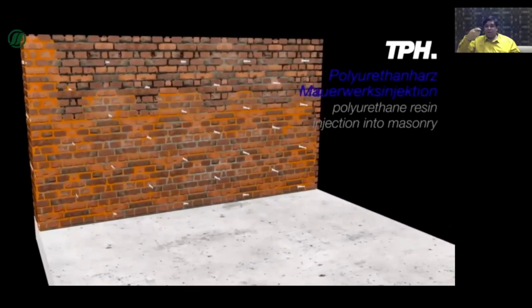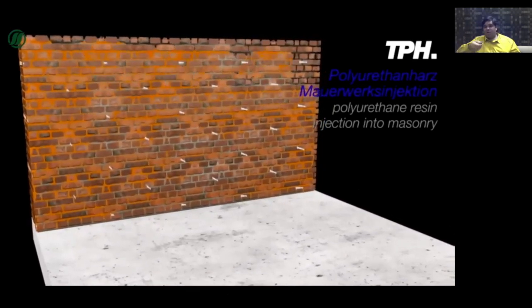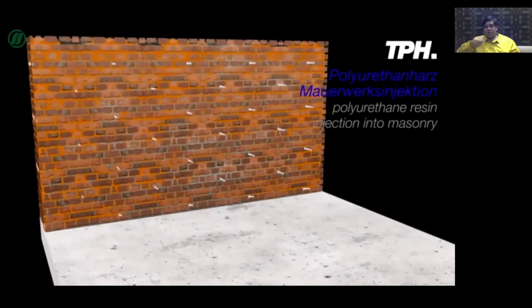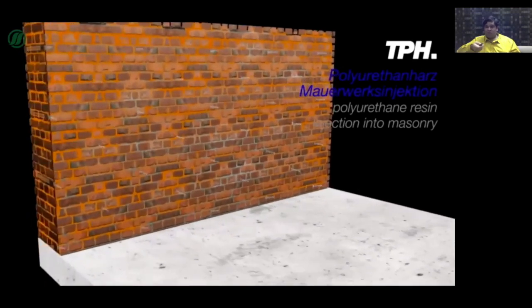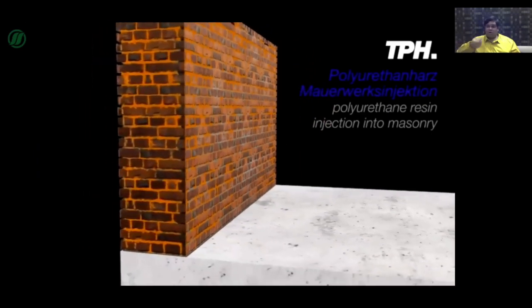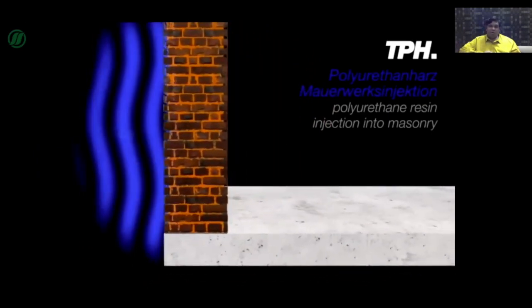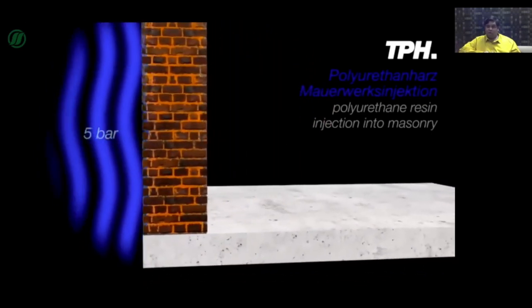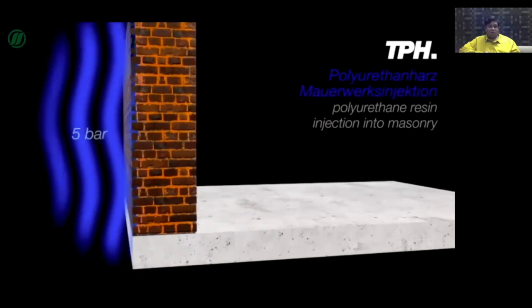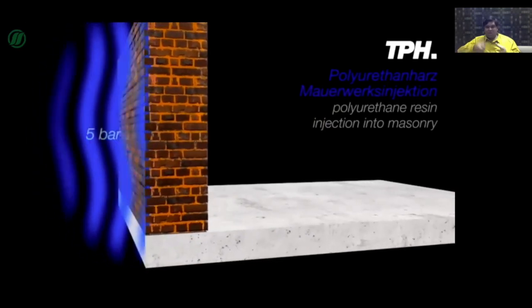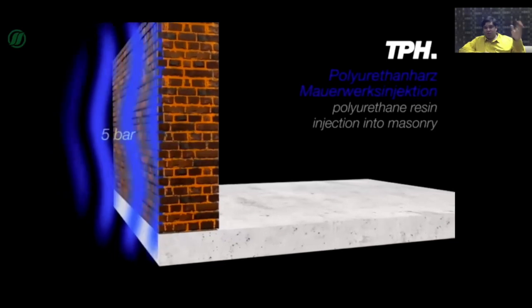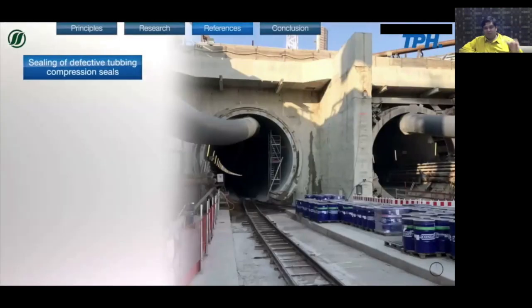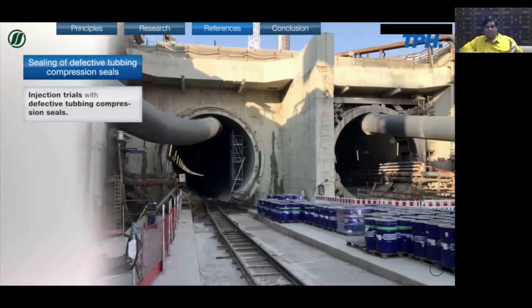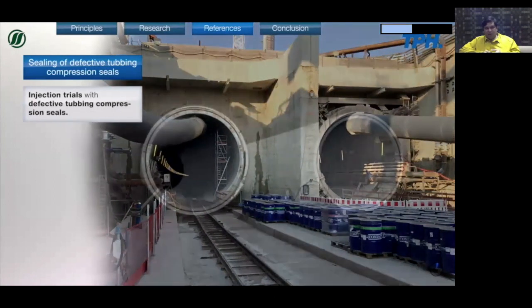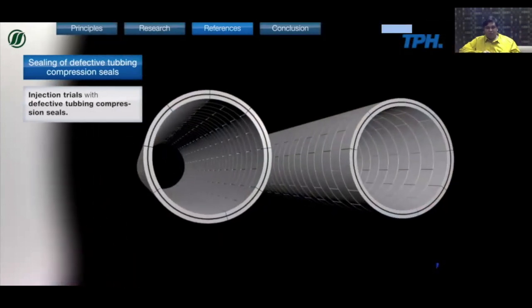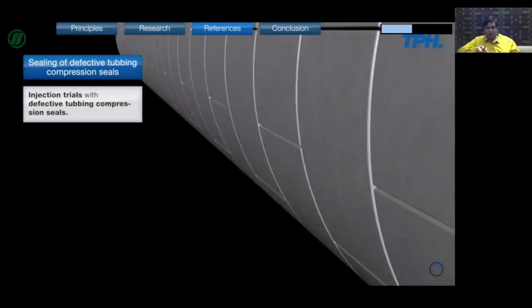If this kind of treatment has been found effective, and in a lot of the tests, it can even resist water up to almost 5 bar pressure. That is almost 50 meters of water head should not be an issue if you are treating the wall in this way. So these are just some different ideas. Like we saw concrete, water tanks, and deep basements. Now this particular case study is a little bit of an offshoot from a metro.